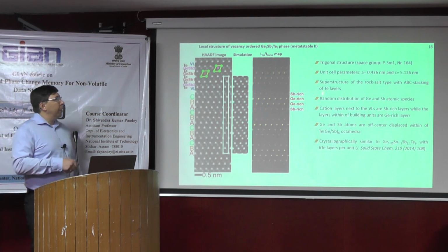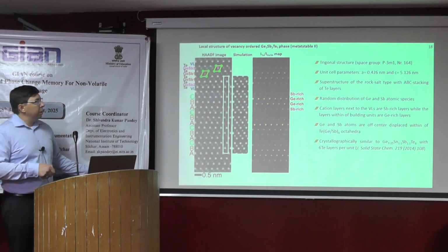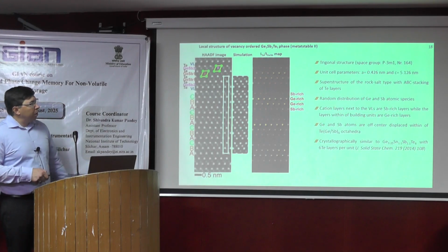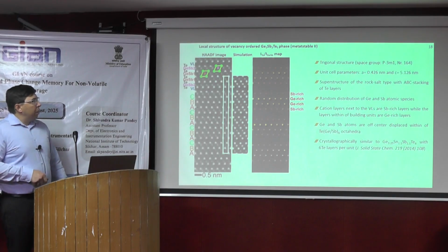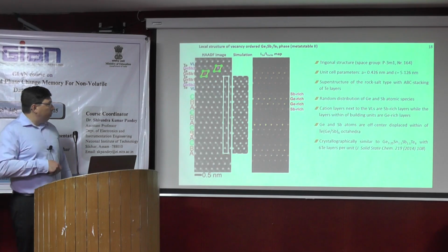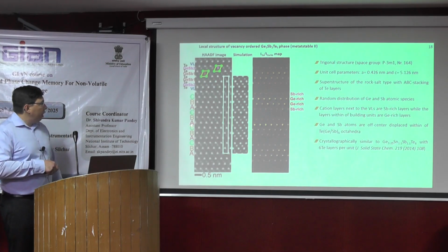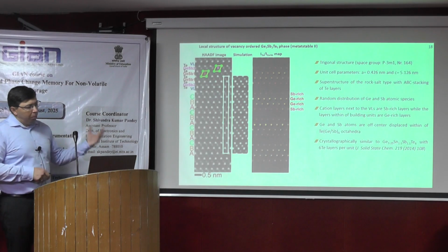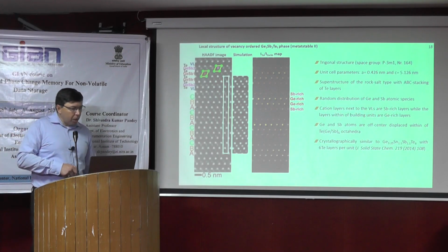The space group and unit cell parameters are a little bit larger compared to the cubic phase, especially c. What we have here is ordering of vacancies into layers. Here the dark lines. The stacking of the layers here is ABC, ABC, ABC, so it remains cubic.